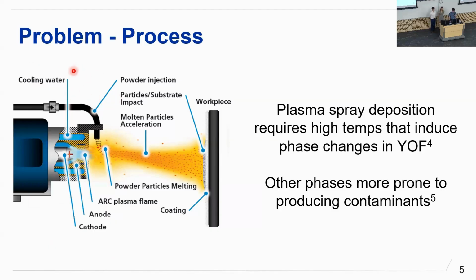Yeah. So the current process being used today is plasma spray deposition. As yttrium particles are accelerated or injected into this plasma arc, they are molten and hit onto the substrate, and then this solidifies and densifies onto the substrate. And the issue with YOF is that this process is about 14,000 Kelvin, which is above the temperature for YOF. So as a result, it induces phase changes, and these phase changes are less desirable than just using yttria. So to actually use YOF, we have to look at a different process entirely.